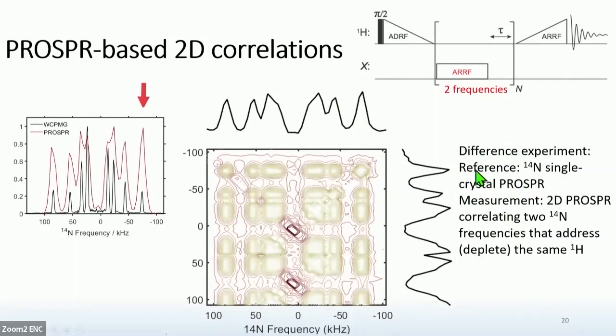And initially, we were surprised by that. But then we realized that whenever we irradiate 2 different frequencies that address the same protons in the unit cell, essentially, it reduces the signal. So the correlation is actually to all of the other peaks that are in the same unit cell. So for this single crystal, it might not be the most useful, but let's say we have 2 single crystals, maybe that can help tell them apart. And we're also excited to maybe use this for heteronuclear correlations, maybe be able to correlate nitrogen and oxygen, or even sulfur and oxygen, which is virtually impossible otherwise.